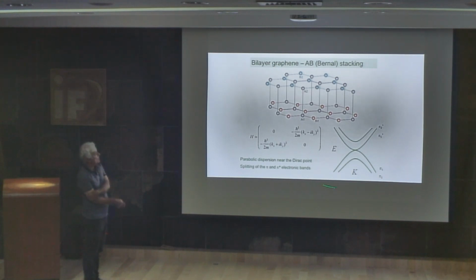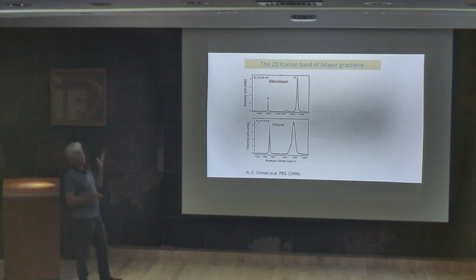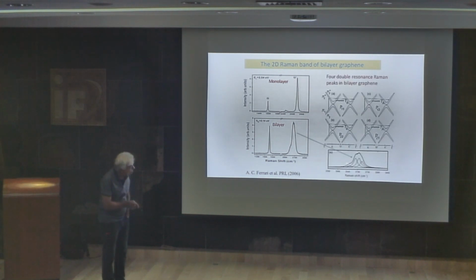And you see that now the electronic dispersion is no more linear, as in the case of one layer, but has a parabolic shape. Since we have two layers, we have 2 valence bands and 2 conduction bands. And this is manifested in the shape of this 2D band. I showed you that the 2D band in one-layer graphene is a very strong peak, but when I have bilayer, you can see that the band is composed of different processes. It is not symmetric and is composed of peaks because in bilayer graphene, since we have two valence bands and 2 conduction bands, we have 4 different possibilities of the process that I showed you.